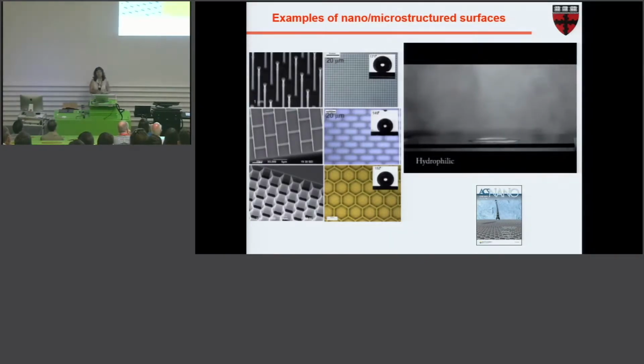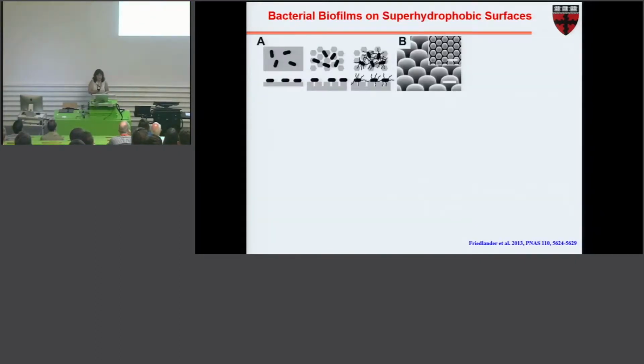What it means is that there are a lot of interesting things happening in the literature trying to reproduce these properties for different applications, in particular those related to biological materials. There is a problem though. So what if I now compare what happens on a flat surface, and let's take bacteria as our proxy in this case, with a structured hydrophobic surface, hoping that if it's structured on a length scale smaller than the size of bacteria, then the contact with these cells is reduced, so adhesion is reduced. So maybe there are fewer cells forming on these surfaces.